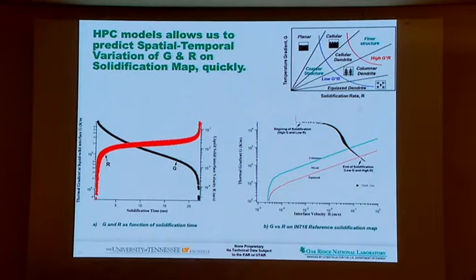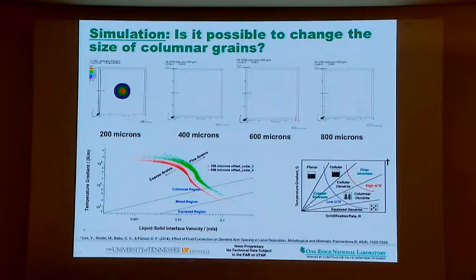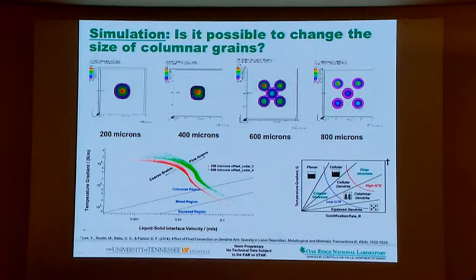When the spots are very close to each other, that is, the bullets are close to each other, it creates a big melt pool. And if you change the distances, you will form individual melt pools. By doing this, you can control the thermal gradient and liquid solid interface velocity. So the first thing Narain said is, Suresh, I can't go into this columnar equiax, let me first demonstrate whether this will take me to control of the grain size. Can I do that first? I said, okay, do it.